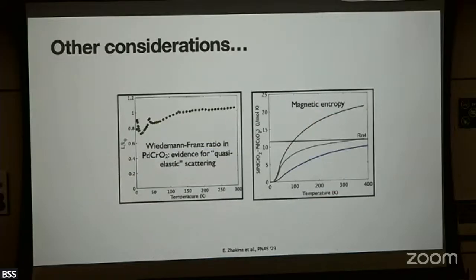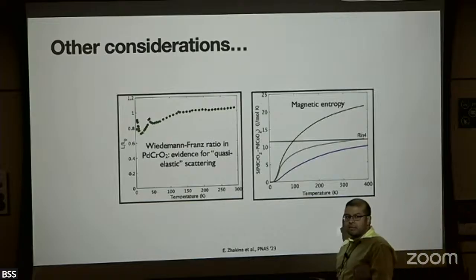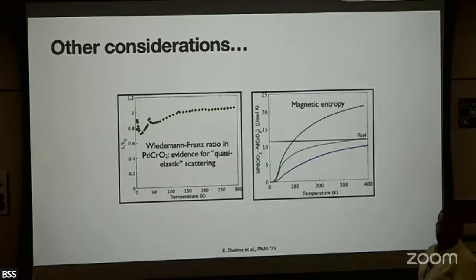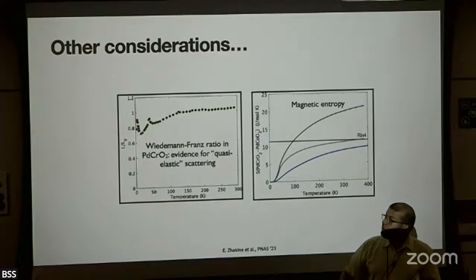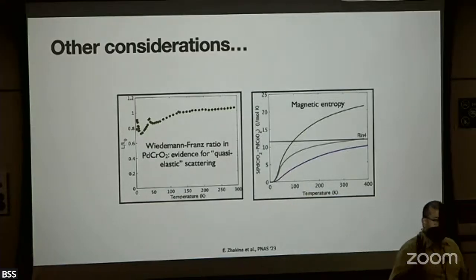Now, is there any indication for why this might actually be the right story for this compound? And the answer is sort of yes, at least it's promising. And that's because you can look at thermal transport. If your scattering is quasi-elastic in the temperature window, for instance, where you see the T-linear resistivity, you would expect the Wiedemann-Franz ratio to be satisfied. I mean, if you think about the original Wiedemann-Franz experiments, they were done at room temperature, right? And indeed, in this compound, L over L naught approaches 1, roughly in the regime where you see T-linear resistivity. So you know that the scattering is quasi-elastic, most likely due to some phonon-induced mechanism, but just not the bare one. The local moments are involved in some way because you have to explain this excess scattering in chromium oxide.